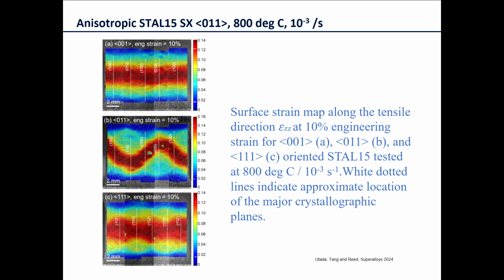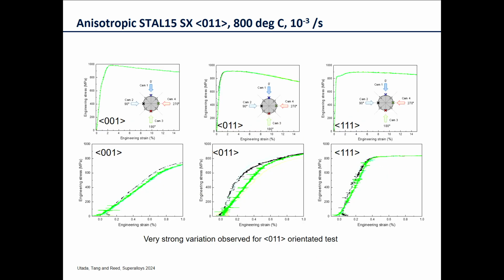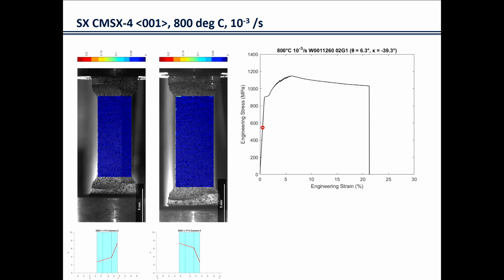And I credit Mr. Utada, who worked very nicely in Jonathan's lab for these very excellent measurements in Oxford. And you can see here that actually the stress-strain behavior in the limit here is very much dependent upon the camera that we use. And this is due to the elastic and the plastic anisotropy of this material and its underlying deformation mechanisms.